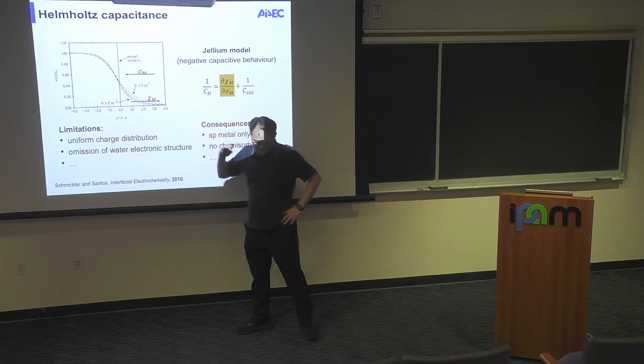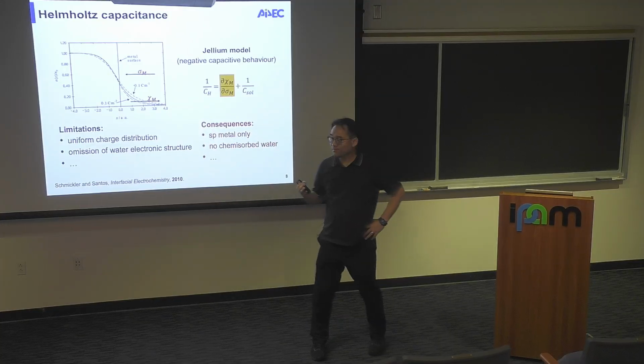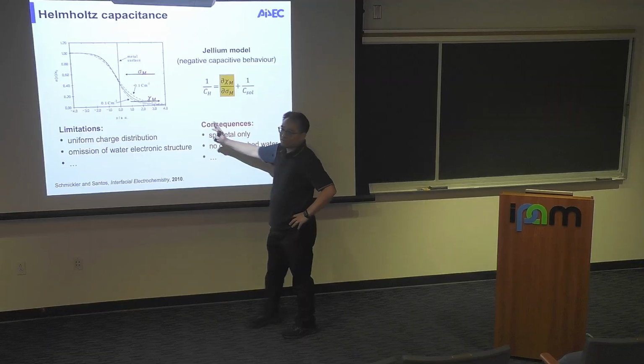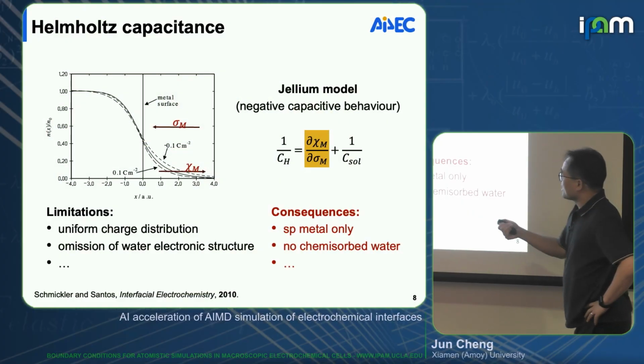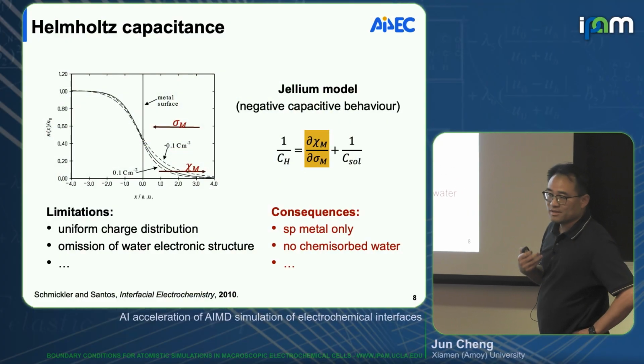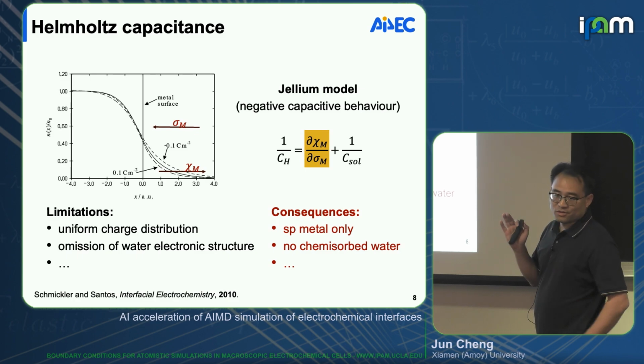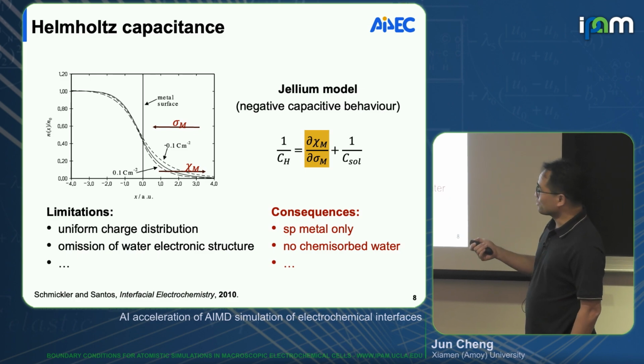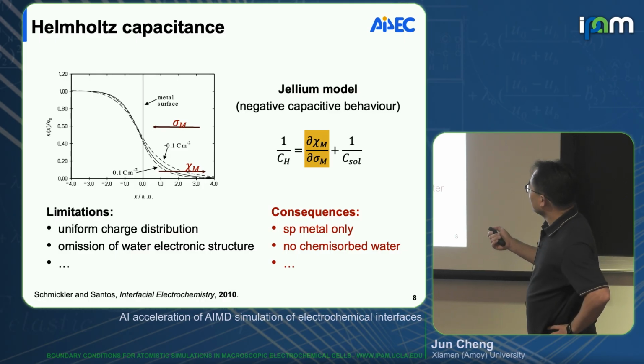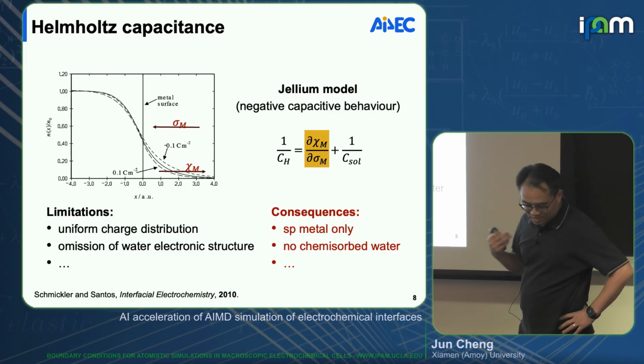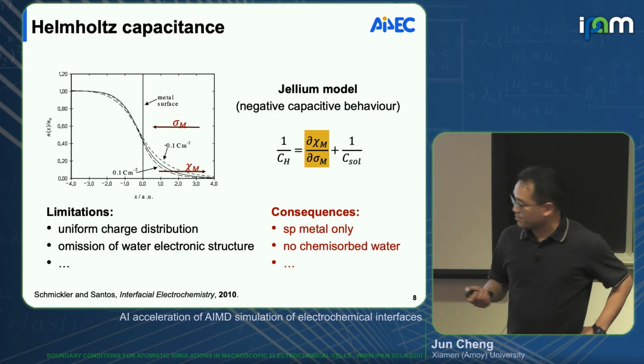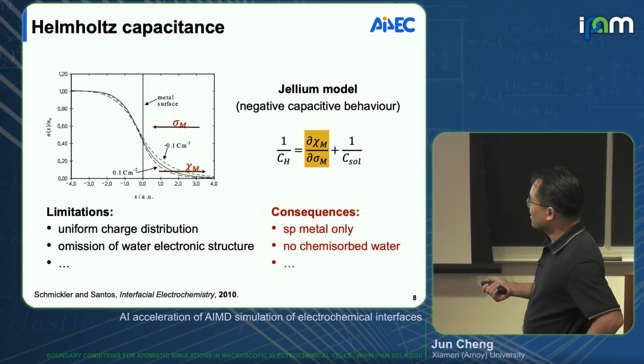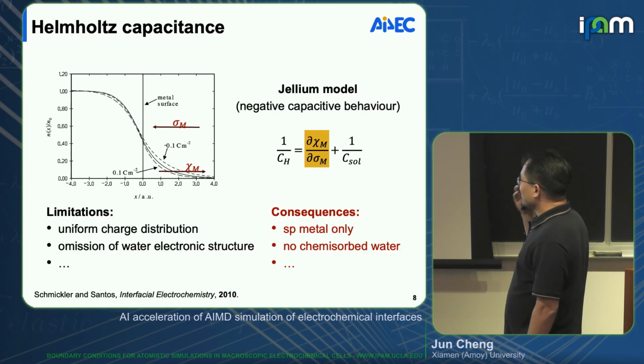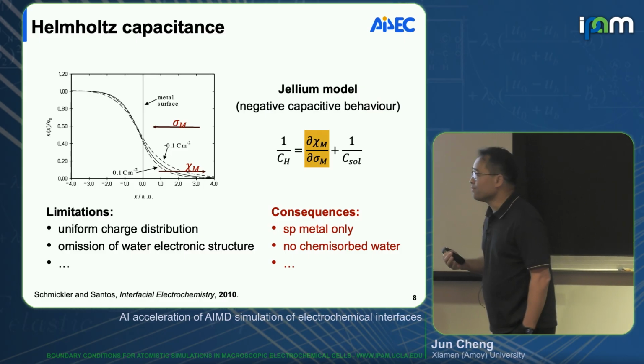In the jellium model, you have electron spill-over into vacuum, so that will create this surface dipole. And in contact with electrolyte solution, that will give you a sort of pushback effect. The electron will transfer back to the electrode. So that will have a dielectric response, right? And through this derivation, Schmickler proposes a negative capacitance behavior. But just to point out that the jellium model is normally good for sp metals.